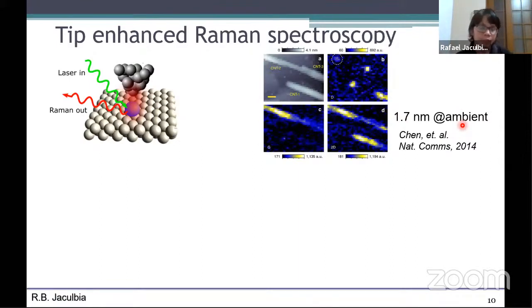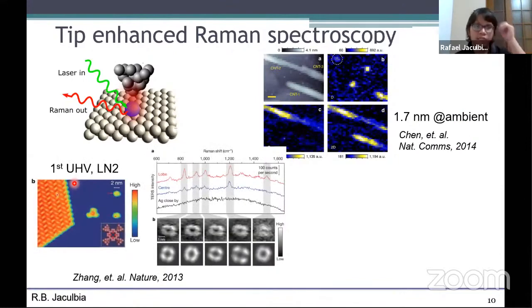This was reported in 2014, but in 2013, the first ultra-high vacuum low temperature TERS, only at liquid nitrogen temperature, was reported. Here they investigated single molecules. For a long time, it was theoretically predicted that because Raman is very chemically sensitive, and with the scanning probe microscope the spatial resolution approaches nanometer or even angstrom scale, if you take the Raman map of a molecule, then individual Raman modes should be different. So it should have different appearance.